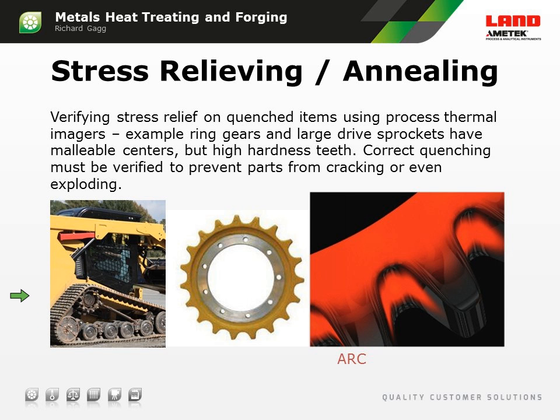Okay, the next one, stress relieving and annealing. So here we can see a construction vehicle, and you see these large sprockets on these things. Again, these things have very hard finishes to the sprocket teeth themselves, but the rest of that wheel has to be very flexible and durable. In this particular case, an arc thermal imager is ideal to see the total circumference of that wheel and the measurement within that circumferential area. You can put a polygonal shaped, a donut shaped sampling area on the outside of that ring gear and sample just the teeth temperatures rather than all of it. This prevents cracking once the part is quenched. It gives a very durable part for use within the vehicle.